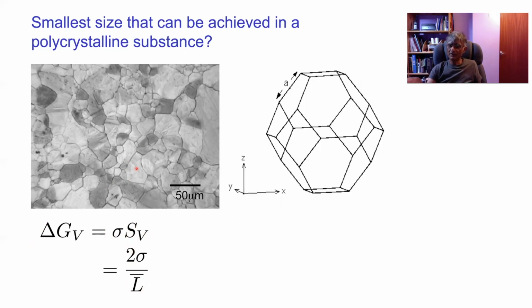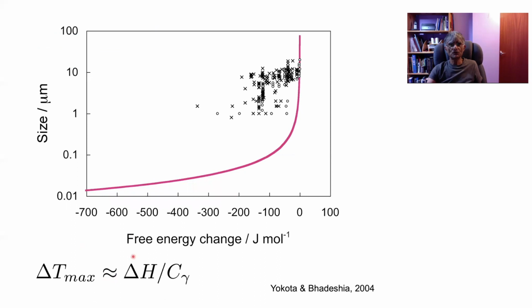So we can calculate the free energy change and set it using thermodynamics and set it equal to this. And then we have a relationship between the smallest possible grain size that can be produced for a given driving force of transformation. In other words, a given undercooling below the equilibrium temperature. So here is the curve showing how the minimum size that could be produced depends on the free energy change. So we would have to undercool to get a size of 0.01 micrometer, which would be very impressive. But it turns out that a large amount of investment to look at this problem never managed to produce a ferrite grain size smaller than 1 micrometer.